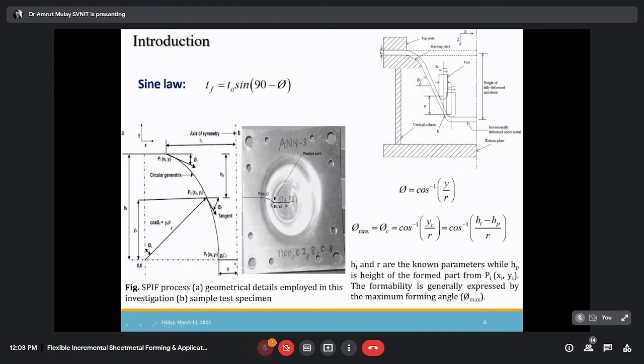One of the limitations of incremental forming is that a cylindrical part cannot be produced. A wall angle of 90 degrees is very difficult. In one or two cases it is possible, but they use another technique. You won't get more formability if you increase the angle. If you make the geometry with 90 degrees, within a small distance in the z direction, it will fracture. So fracture has to be avoided in forming, which is a very big challenge in front of researchers worldwide. Avoiding the fracture. So what are the different ways that you can predict the fracture?